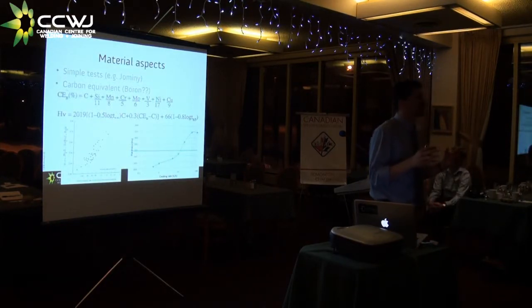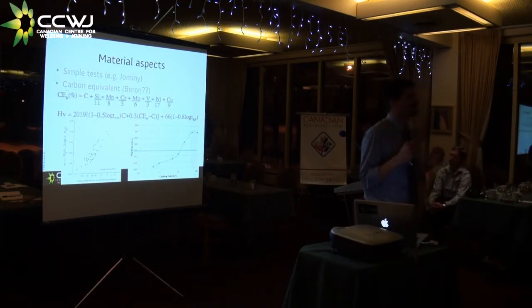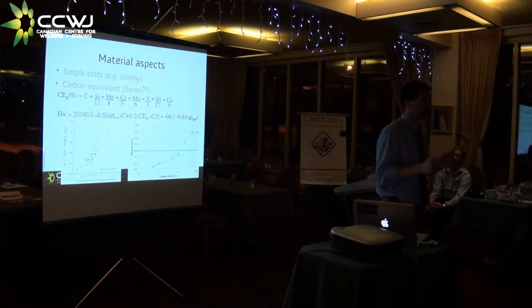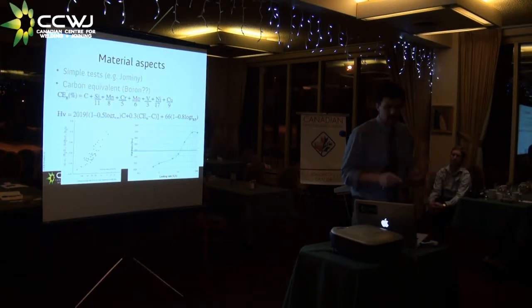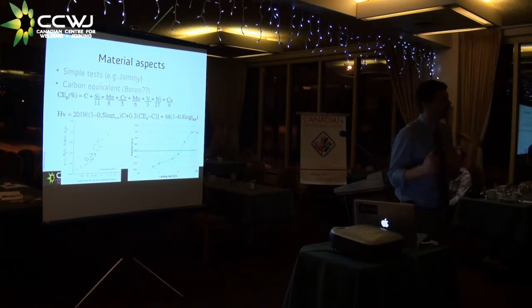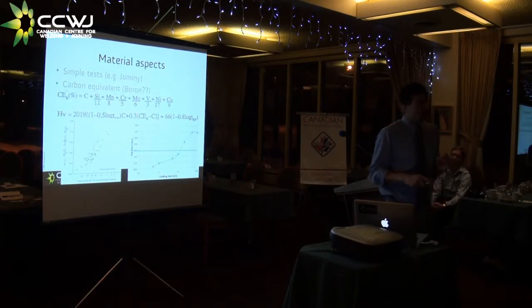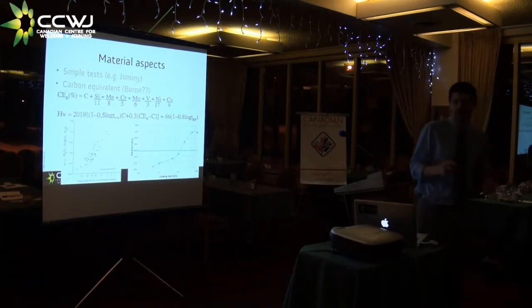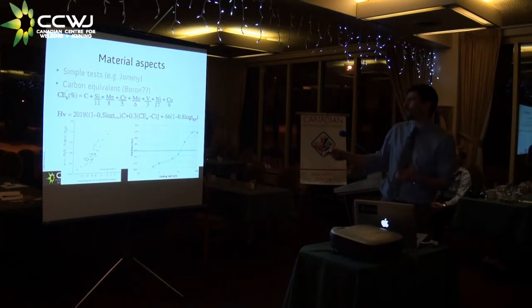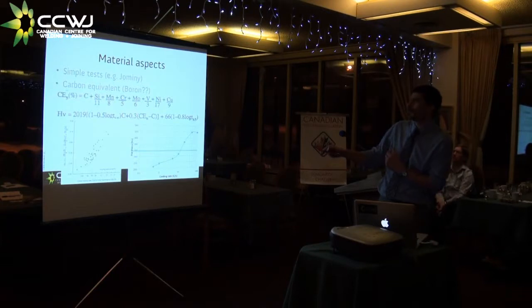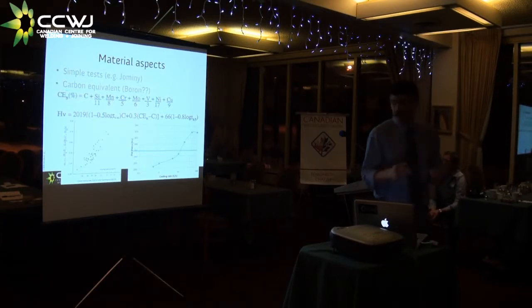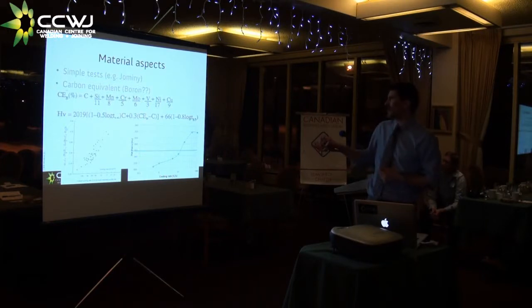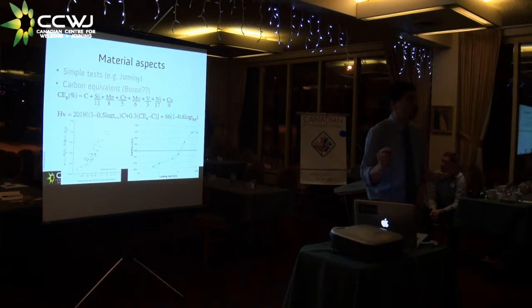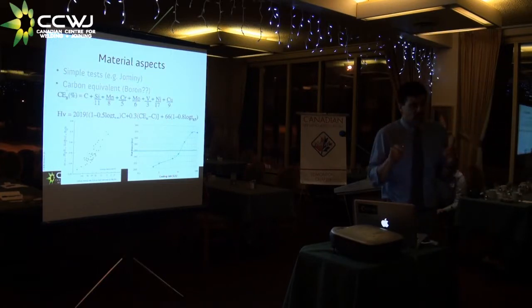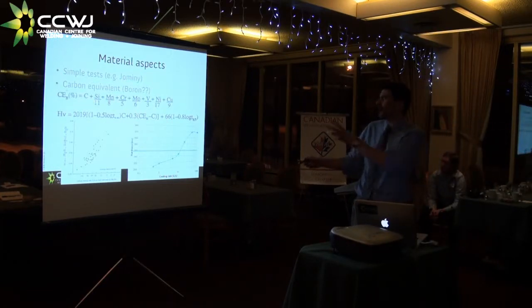All these curves are typically made for steels that are heat treatable. Heat treatable steels are the steels you don't want to weld, right? Like 4340. The funny thing is that for welding we seldom have the CCT curves, right? But we have something similar that is the carbon equivalent. With the carbon equivalent, we can say if I have a given composition, I would get a given carbon equivalent, and there are formulas that say if you have a given carbon equivalent and a given cooling rate or a T8/5, however you want to measure it, you would end up having a given hardness, right?